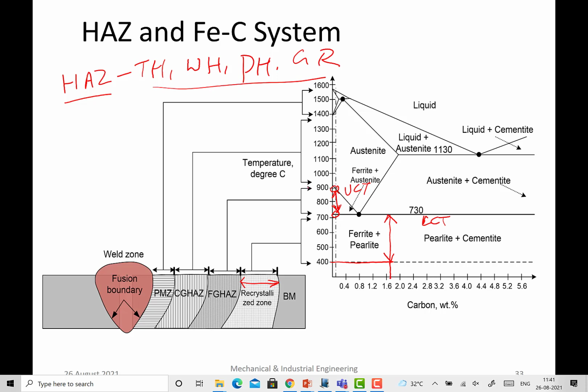So this is your intercritical temperature range, and this is the range where you will be finding the very fine grain structure, okay. And when metal is heated above this, 910 or 900 up to this, this is another band where you will be getting the austenitic state. This is the range where you will be finding the coarsening. The higher the temperature, the greater the coarsening of the grains.